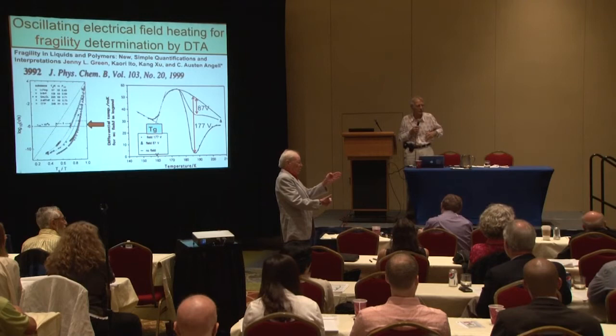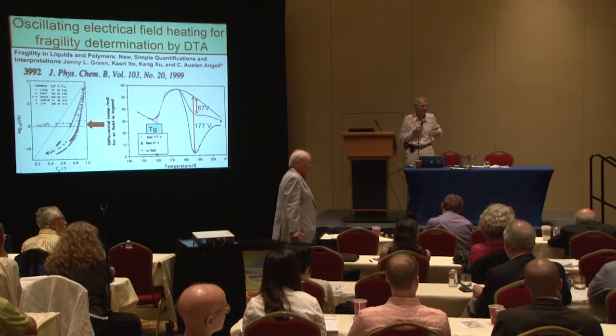I was just going to quickly ask, is not the non-fragility of silica glasses generally attributed to the fact that it's a covalently bonded glass as opposed to an ionic bond? No, that's not good, because beryllium fluoride is the younger brother of silica, but it's totally ionic and it behaves in the same way. It's to do with the ability of the structure to resist degradation under temperature, which is involved.